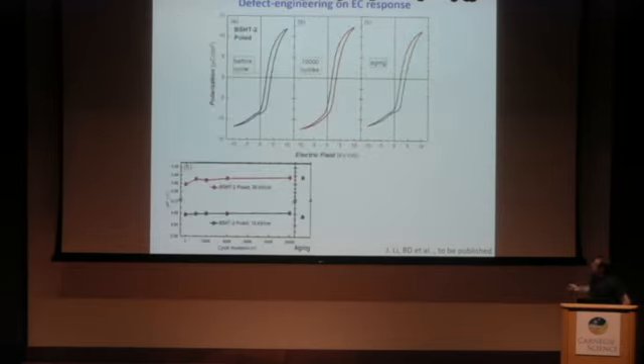We did also the same kind of things. I will not go into the details here, but we played also with this hysteresis loop to see how the delta T evolved as a function of the number of cycles. And there is a very nice stability of this delta T, meaning that we, I guess, are ready to use this kind of devices, even if delta T in that case is not so big.